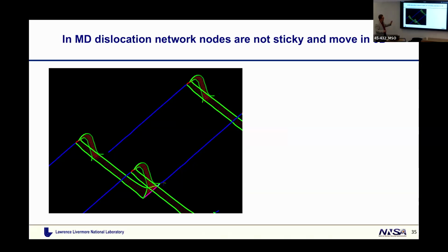What we're going to see is a simulation of a fragment of a dislocation network in FCC. And classically, these nodes can only move along the blue lines. You will see that something happens which was not known before. In fact, a completely new mechanism of dislocation reaction was discovered, where these nodes manage to move in 3 dimensions.